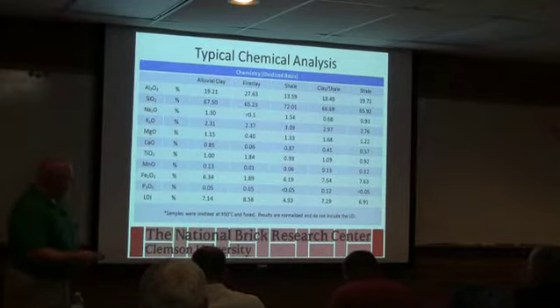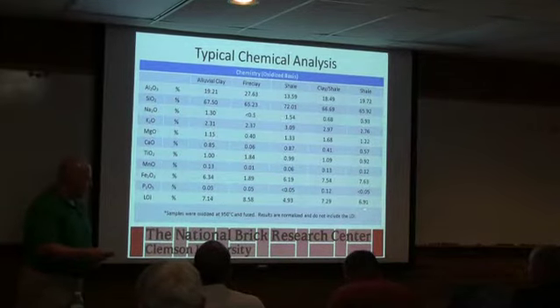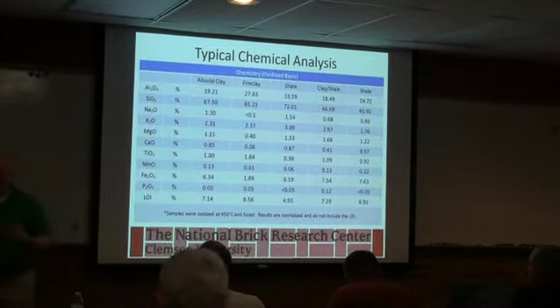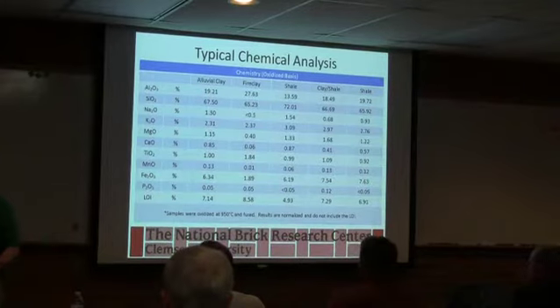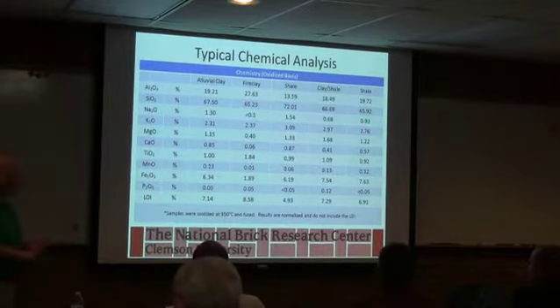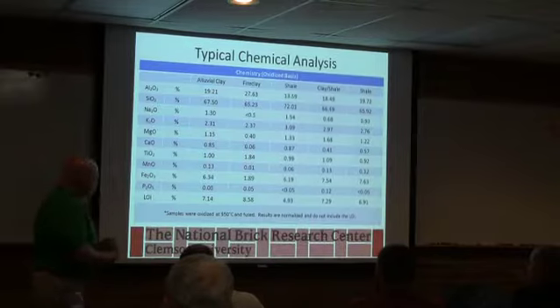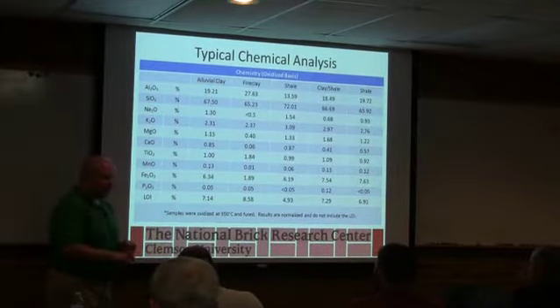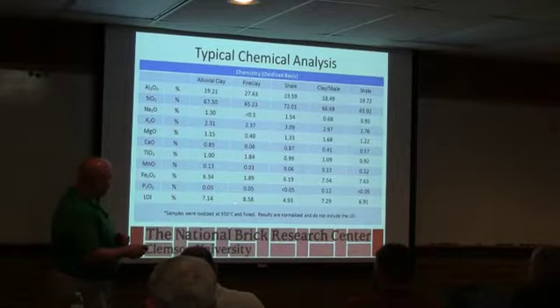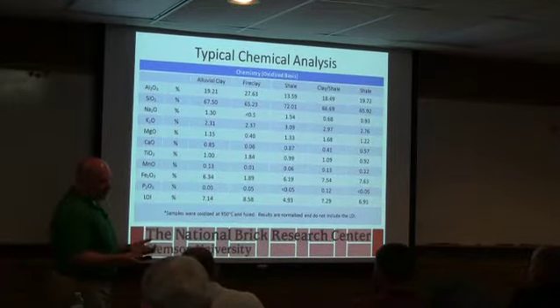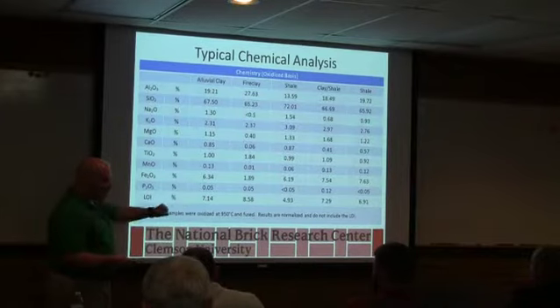And then this loss on ignition. That's always something we measure on the raw materials. It's basically how much weight the brick's going to lose going through the kiln. And that can be from a lot of things. Primarily, it has to do with the clay mineral breaking down. So again, that number can be an indication of clay content. So you see the material I said with the highest alumina also had the highest loss on ignition, goes together. That's probably got a lot of clay mineral.